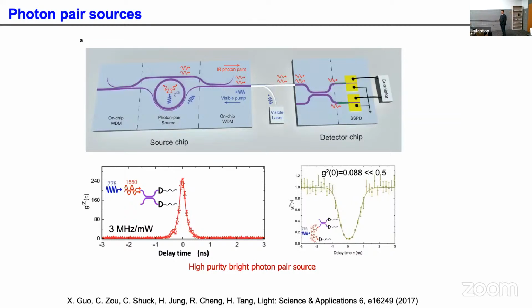So that's the OPO. If you drive the OPO just at threshold, you would have a squeezer, and measurement of squeezing is much harder. So the way we try to quantify this OPO is at very low pump powers, by measuring photon pairs. You can drive even below the OPO threshold, far below the pump required for squeezing, and generate photon pairs. You can use the pair of detectors I showed you earlier to analyze the photons you generated. This experiment shows that you can produce a very bright photon pair source with these kinds of second harmonic generator or OPO devices.